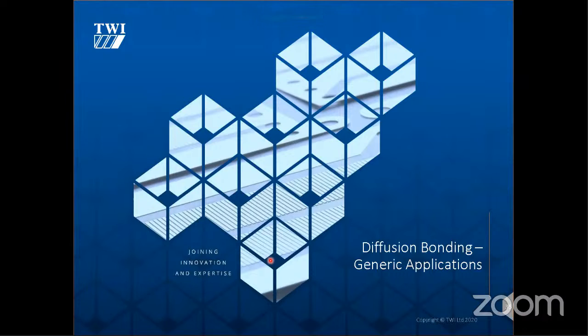What kind of surface preparation and finish is required for diffusion bonding? Very good question. So that ultimately, as with most of these answers, is dependent on the materials, the grades, and the process you're using. If you're using a transient liquid phase process, you can get away with slightly rougher, slightly less parallel surfaces because you have the molten phase.